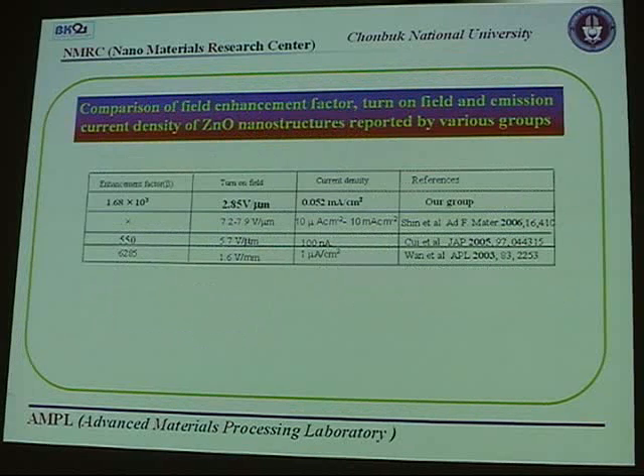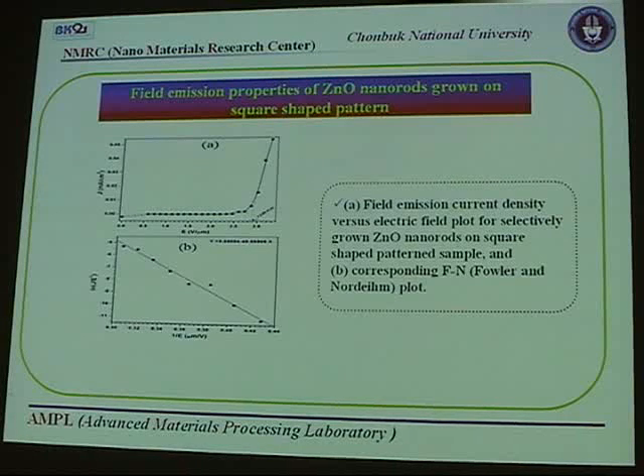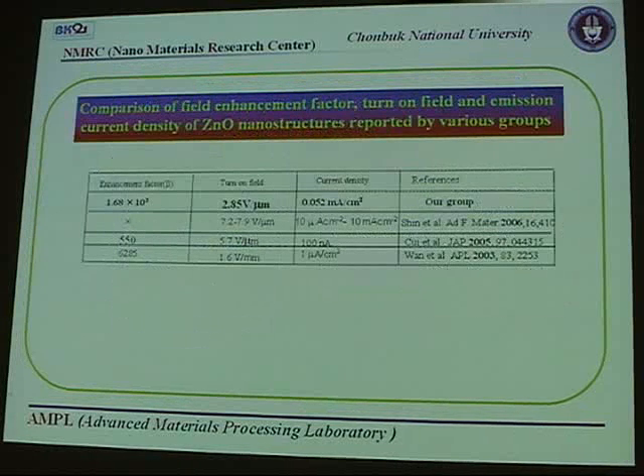We have compared this data with data recently published by other people on zinc oxide, by Shin et al. in Advanced Materials last year. They show a current density equal to 10 microampere per square centimeter, but we have achieved a good current density of 0.052 milliampere per square centimeter and a very low turn-on field using a very simple and novel solution technique, which suggests that these zinc oxide nanorods can be a good candidate for field emission devices.